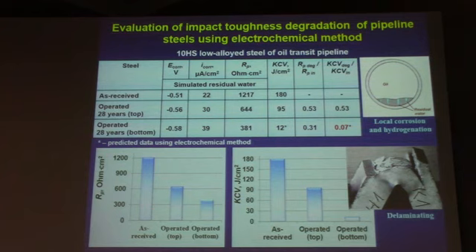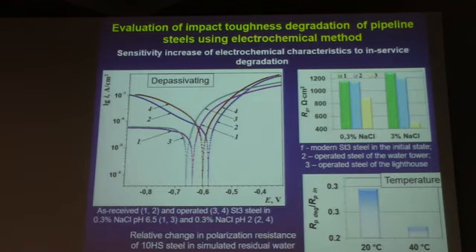And presented here data show that long-term corrosion caused a decrease in both electrochemical and impact strength characteristics for the material. And it was impossible to determine impact strength of the bottom section steel in the laboratory due to delamination, and the data presented here was predicted using the electrochemical method based on correlation between relative changes in polarization resistance and impact toughness.